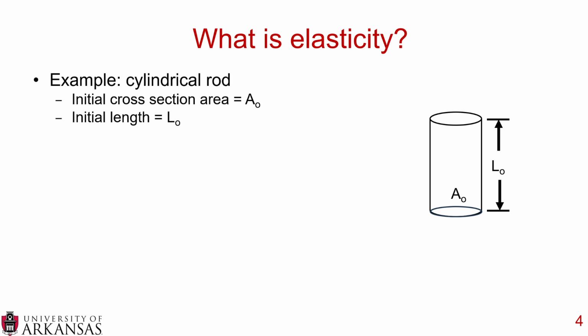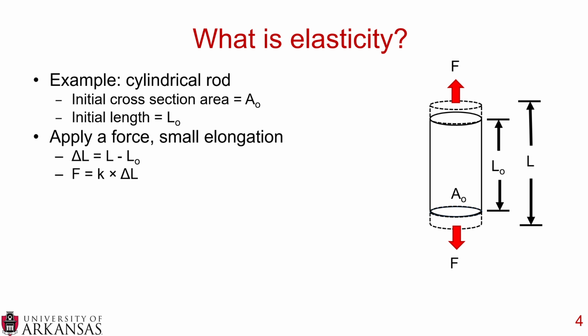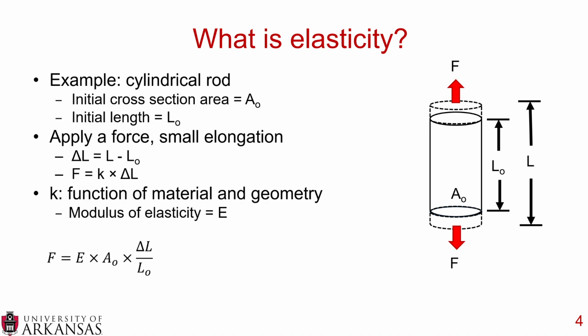What is elasticity? Well, in order to show what elasticity is, let's look at a cylindrical rod that has an initial cross-section area A0 and an initial length of L0. Then let's apply a force, and we get a small elongation. So we get a delta L, which is L minus L0, and the force we applied is K times delta L. And that K is a function of material and geometry, and specifically the modulus of elasticity. And so we can substitute into K E times A0, so we have the force equaling E, the modulus of elasticity, times A0 times delta L over L0.